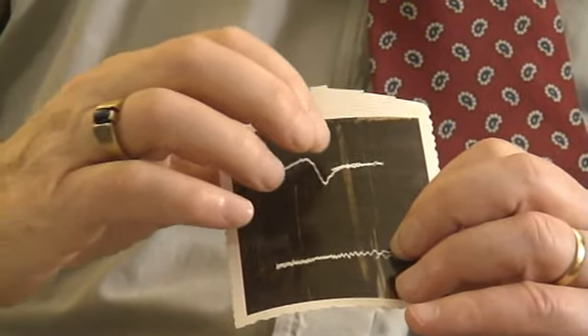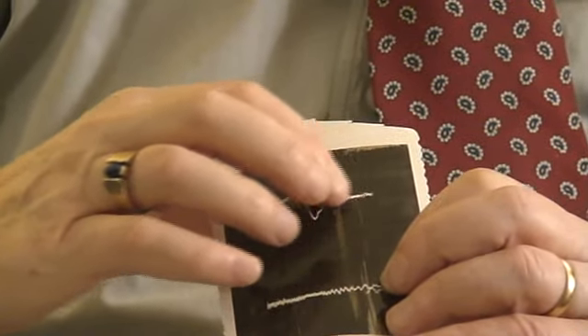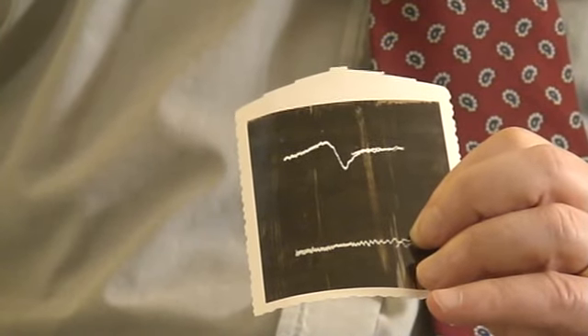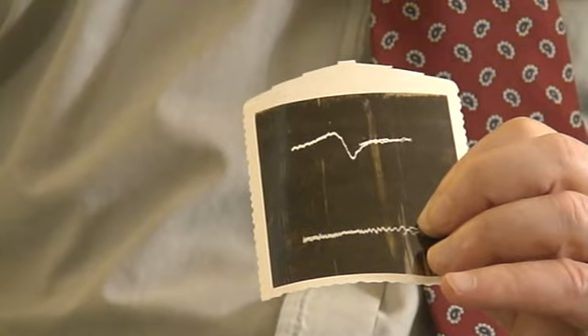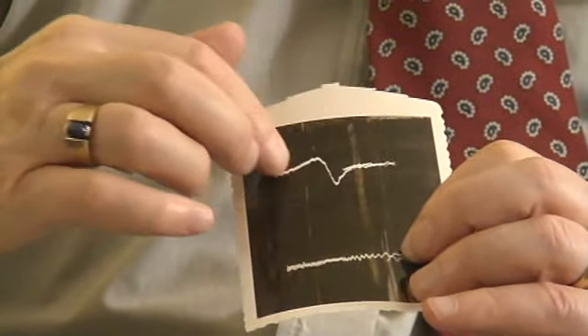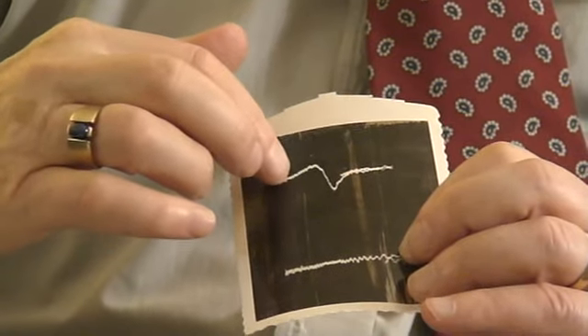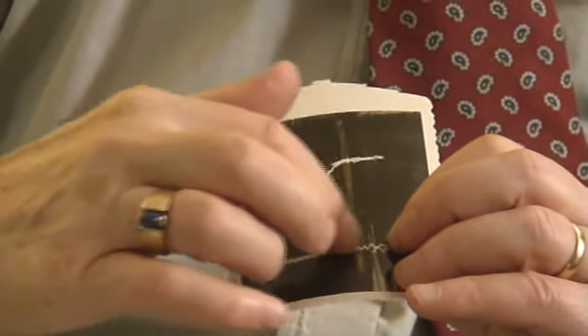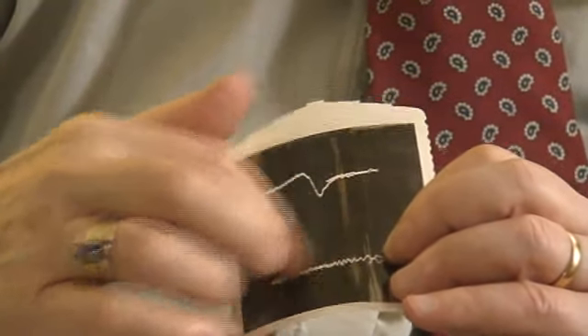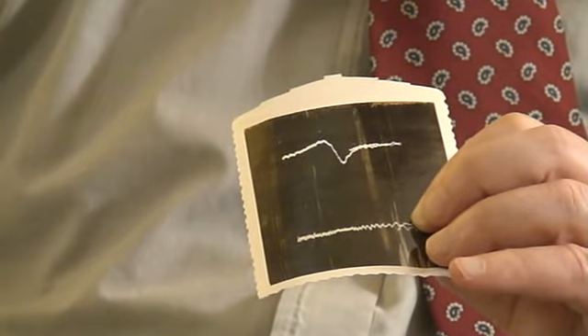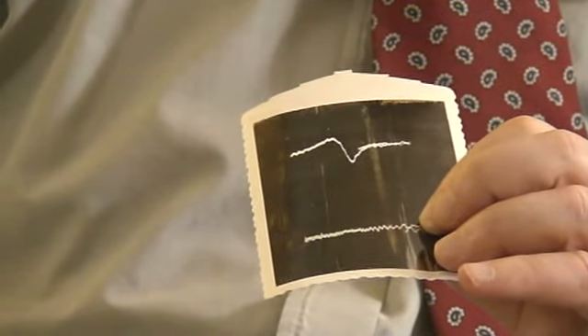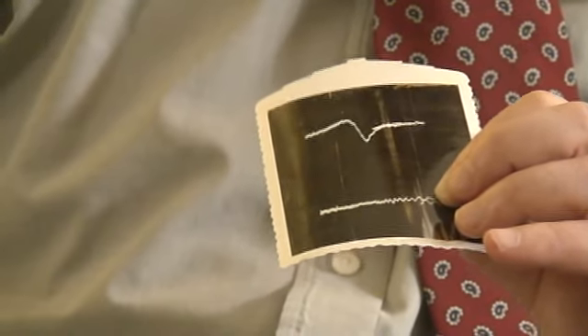And since the experimental sensitivity was measured quantitatively before this experiment was done, they were able to decide that this resonance was 100 times larger than what it is in this line here. 100 times smaller than that would not show up at all. But the factor of 100 was what was predicted for the intensity of microwaves that they had available to them. So I believe that this Polaroid picture of the actual resonance probably came to me with this letter.